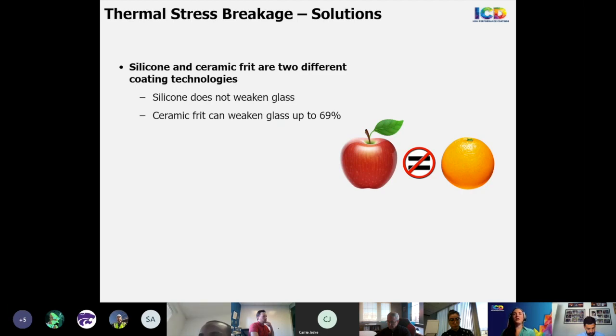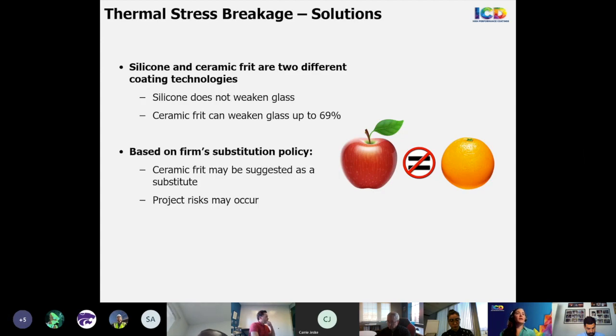Both Frit and silicone are great choices for use on facades and are very trusted and perform well, but they do have their differences. And the one that was discussed today was about weakening effects. And that 69% is actually referring to the including the impact resistance of glass. As we saw earlier, the tensile strength reduction is about 40 to 50%.